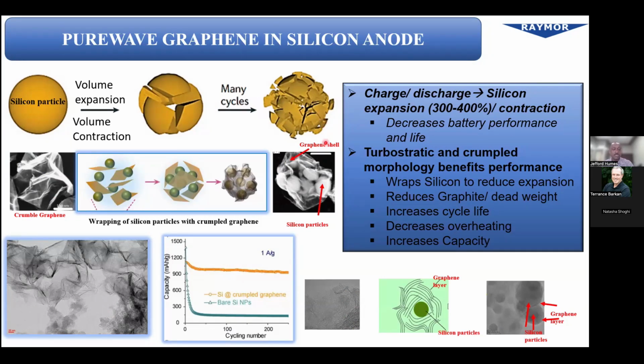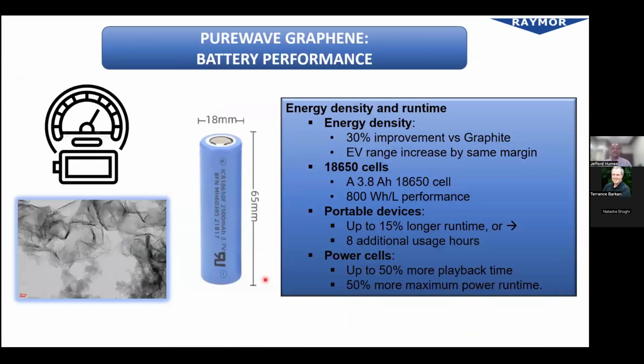With our Purewave graphene and its turbostratic morphology, what has been found is that our graphene is actually able to wrap the silicon particles to reduce this expansion substantially. It reduces, therefore, graphite usage and dead weight in the battery, increasing cycle life, decreasing overheating, and increasing capacity, as can be seen within this research that was done at Northwestern University. We're very proud to be partnered with a battery materials company that actually uses our graphene within their silicon-based batteries.